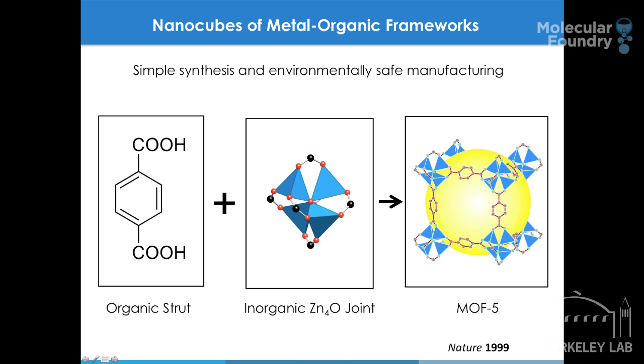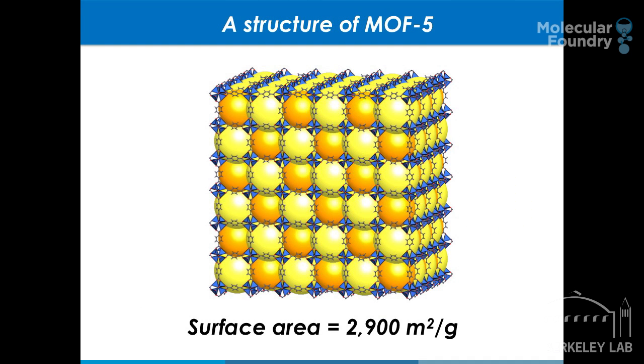We published in 1999, and it was the beginning of the MOF field because in MOF-5, if one looks at the structure as a whole, it's an extended structure in which organic units are the struts and the inorganic units, or the multi-metal units, are the intersections, forming again a rigid architecture. The yellow balls in this figure indicate the space within which gas molecules and small molecules can reside. The pore opening here is on the order of 1 nanometer, and the internal pore is not very much larger than that. The surface area we found, surprisingly, was 2,900 square meters per gram.